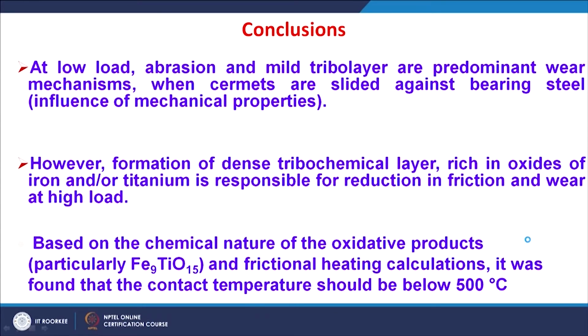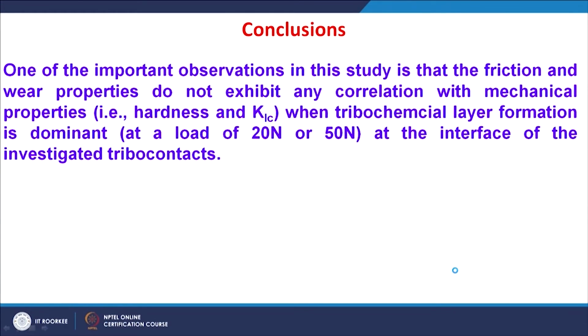Regarding the mechanism, at lower load the abrasion and mild tribo layer are predominant. However, the formation of a dense tribochemical layer, which is rich in oxides of iron and titanium, is responsible for the reduction in the friction and wear at higher loads. So, based on the chemical nature of these oxidative products and the frictional heating calculations, it was found that the contact temperature should be below 500 Celsius.